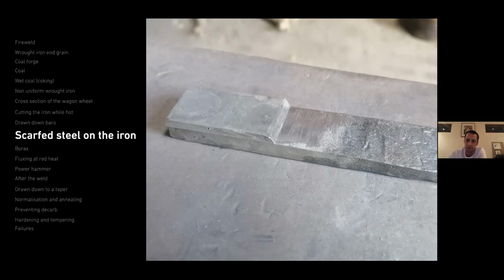Overheating this billet would basically ruin the hard steel, it would burn it. And not heating it enough, it just would not stick to the iron, and the iron can also crack if forged under low temperatures.